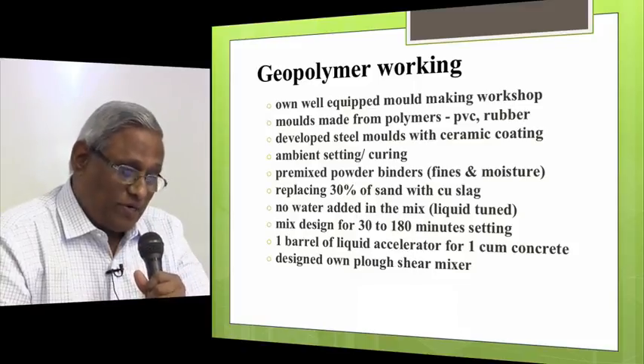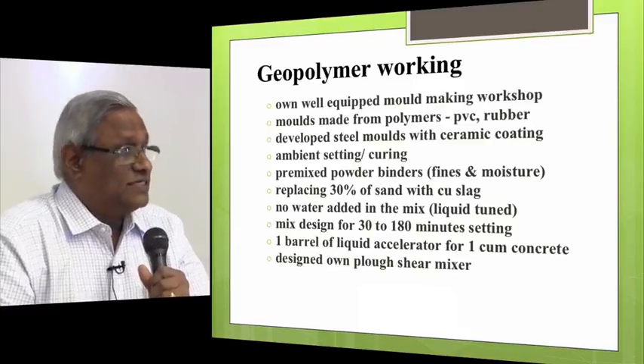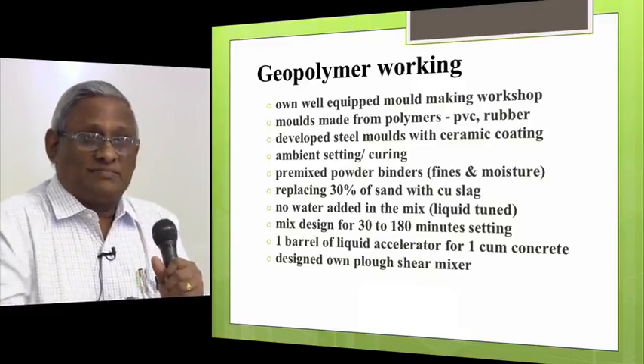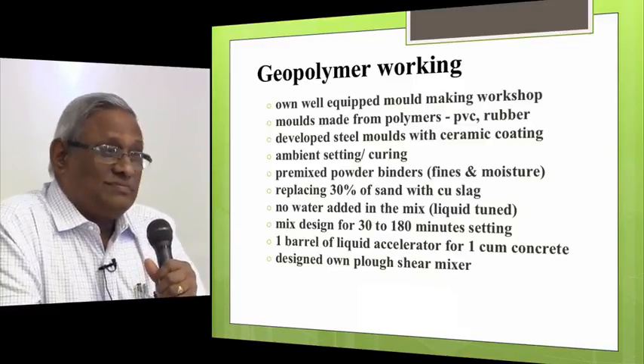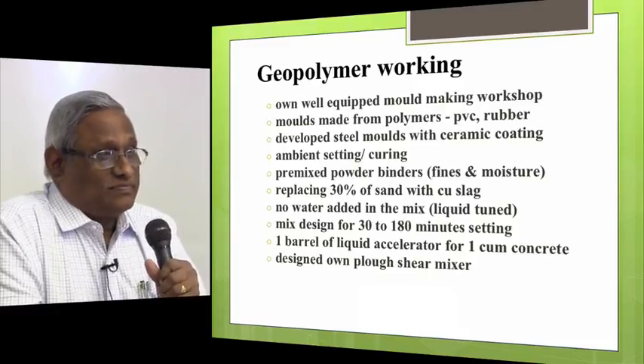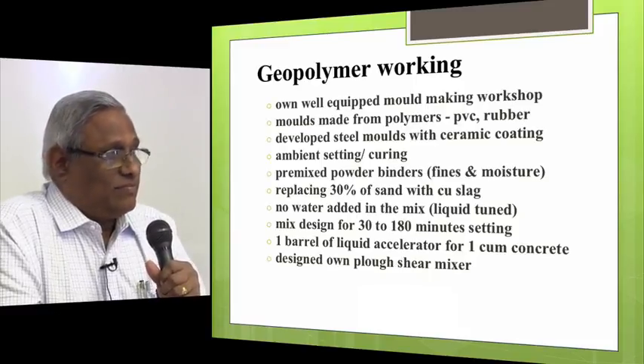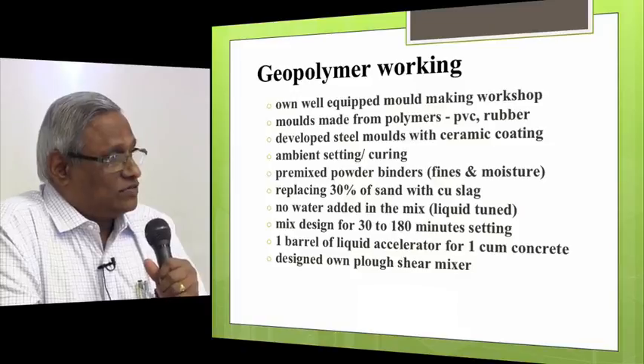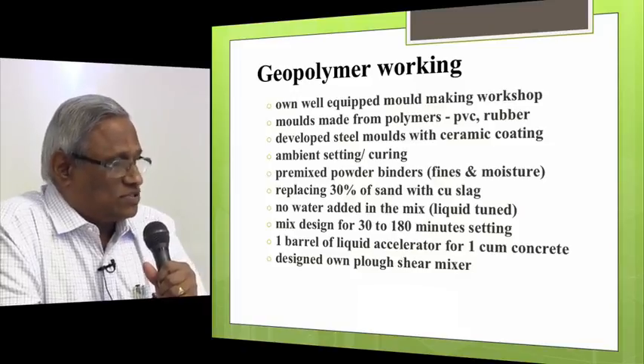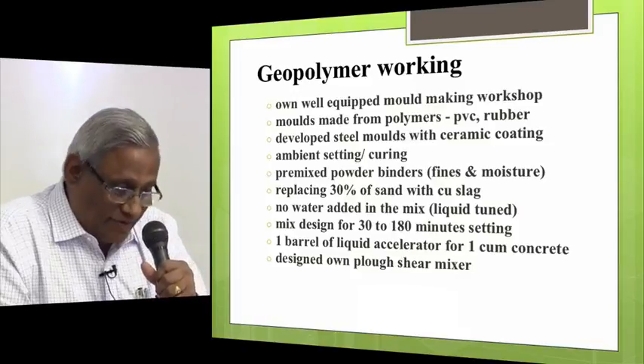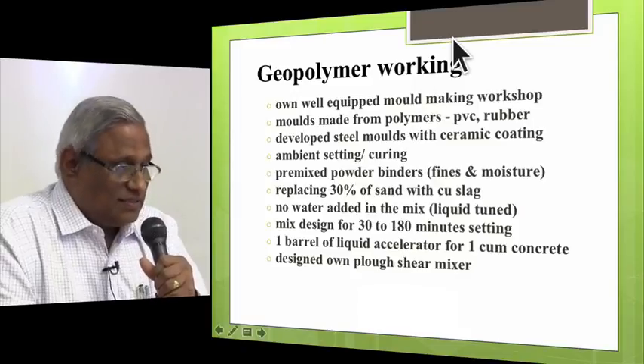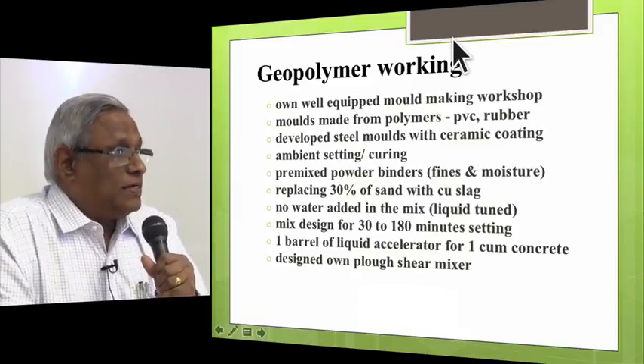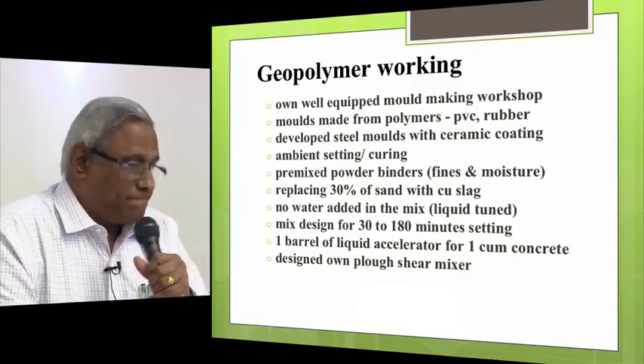And another very important aspect why this shear mixer is used is when we add pigments. The pigments get a very good dispersion, so it's very useful. And we have made mixers right from a batching size of about 100 kilos to 1,000 kilos. And we are using the same mixer now for a ready-mix concrete batching plant.